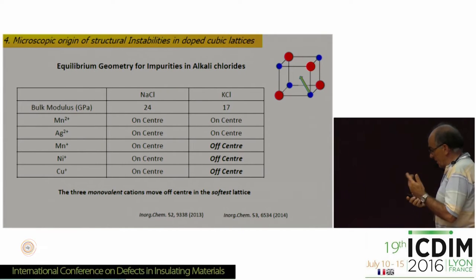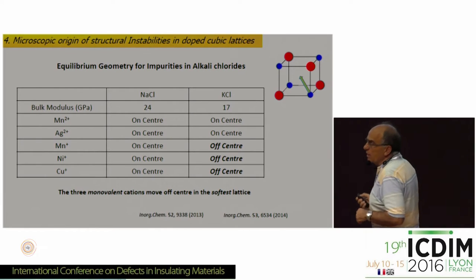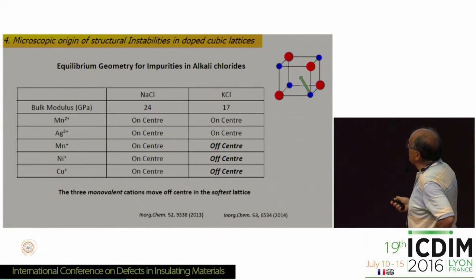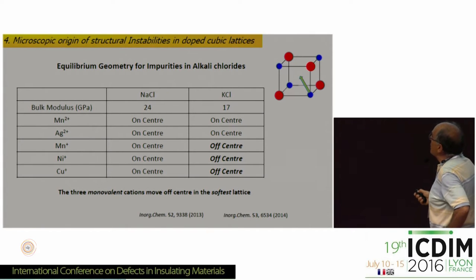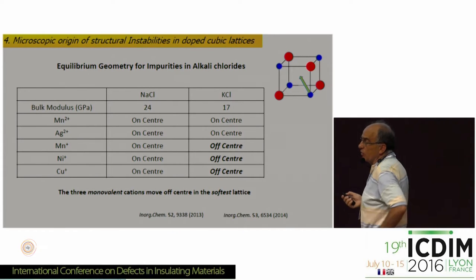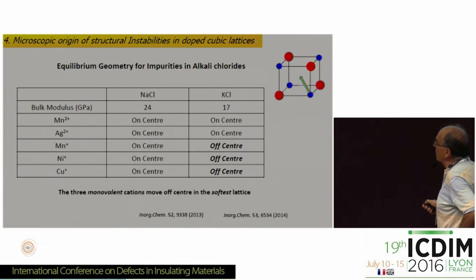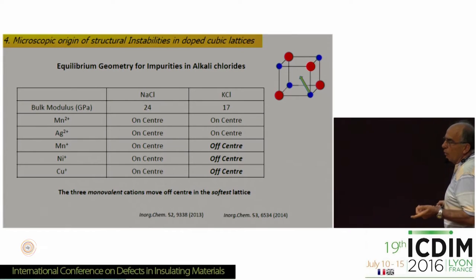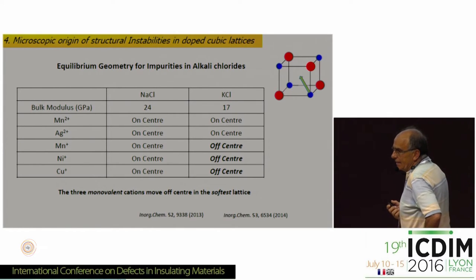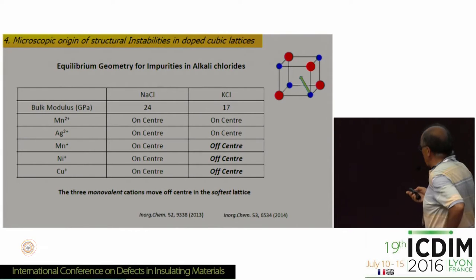Moving to systems with rock salt structure: the bulk modulus of sodium chloride is about 50% higher than potassium chloride. All impurities in sodium chloride remain on-center. But in potassium chloride, the three monovalent ions move off-center — only the monovalent, not the divalent.